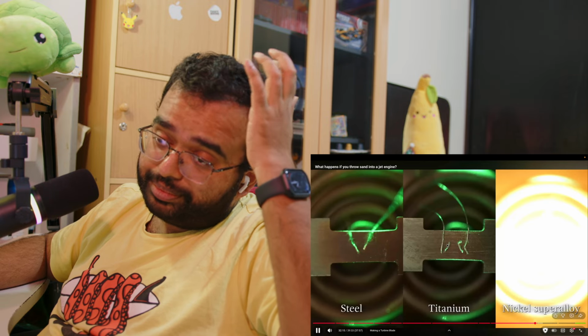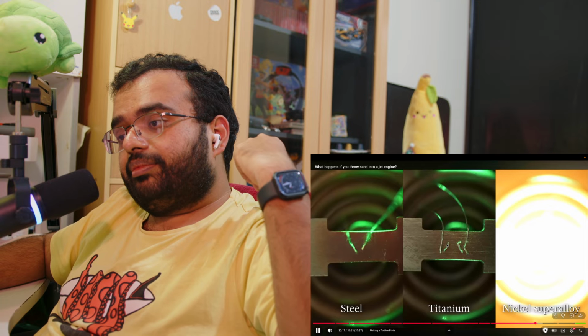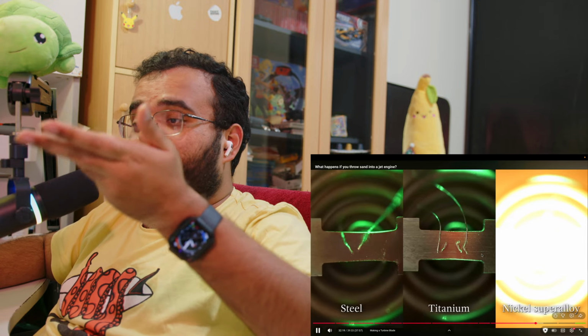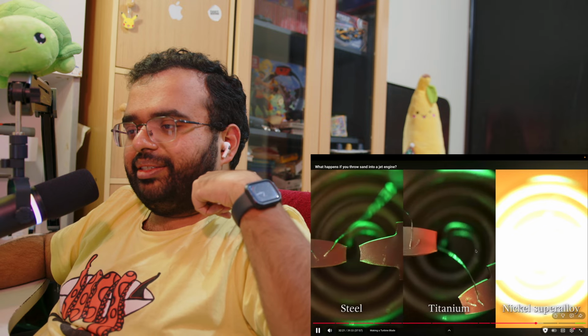People would know. In the furnace, the nickel superalloy outperforms all the other samples, surviving up to 1,200 degrees Celsius. But wait, that's still 300 degrees less than the temperature inside a jet engine. I was going to say, you saw them fail at 1,200. How are they standing 1,500 degrees inside a jet engine? So why don't the blades melt?